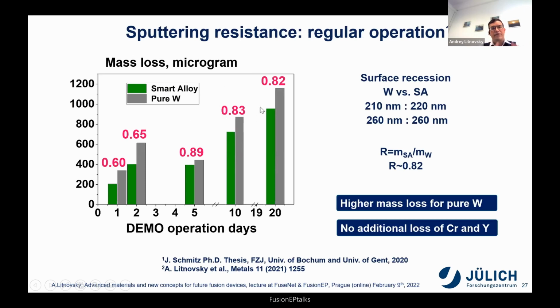This number shows if we sputter this in our model system and nothing happens with the smart alloy, it will be sputtered as we predicted, with no additional parasitic transport of the alloying elements which can increase the sputtering. The ratio of the mass of smart alloy to tungsten should be around 0.82. And this is what we see. In fact, no additional measurable losses of the alloying elements, which we need for our accident scenario, were measured in this experiment. And this is a good result.